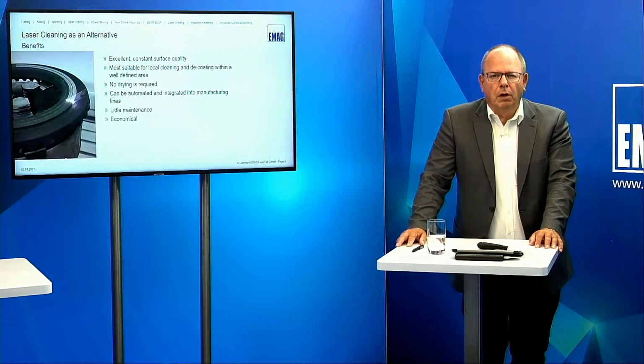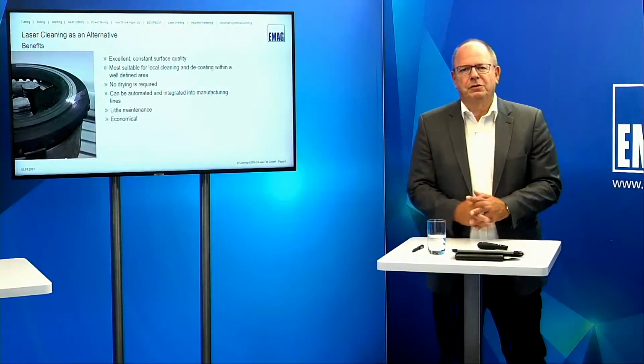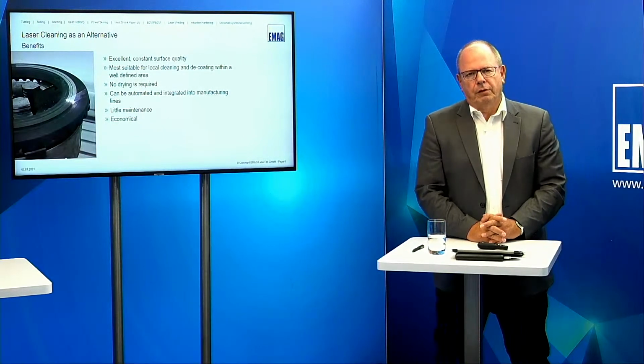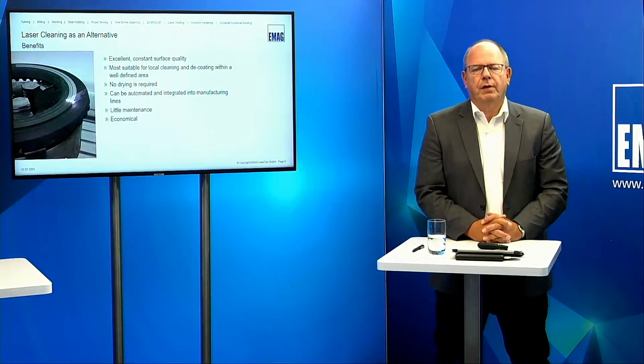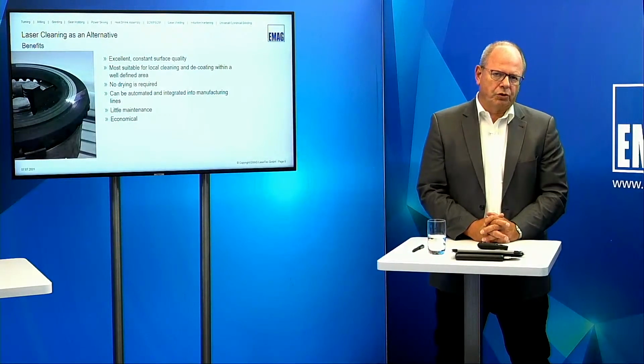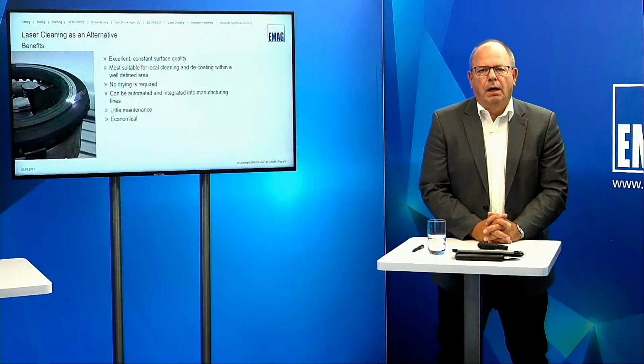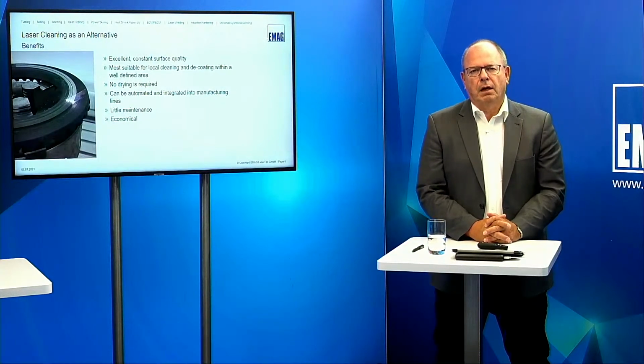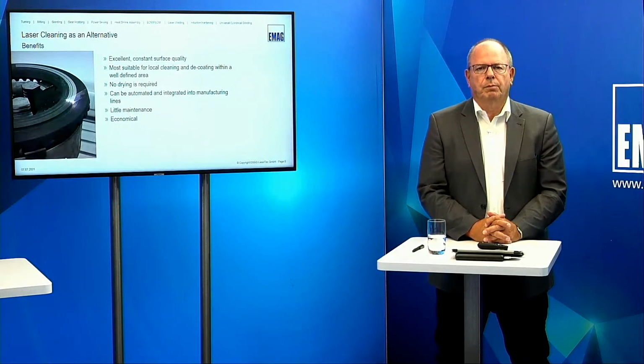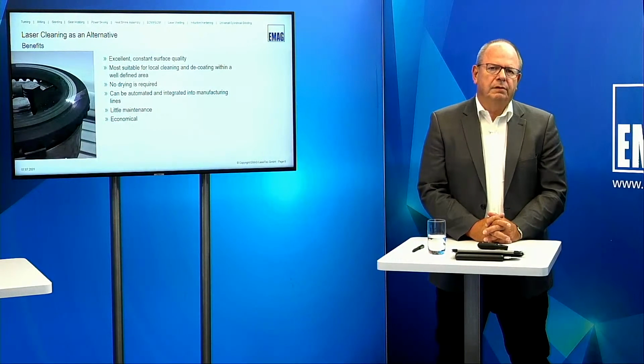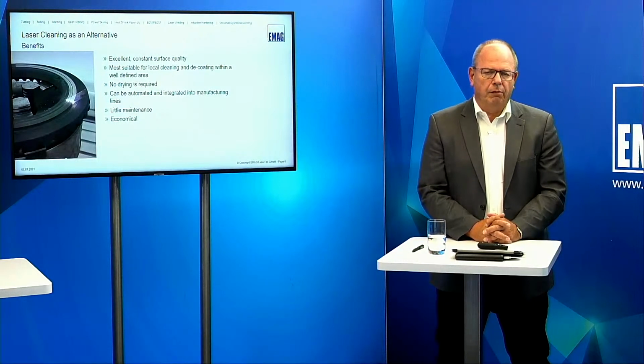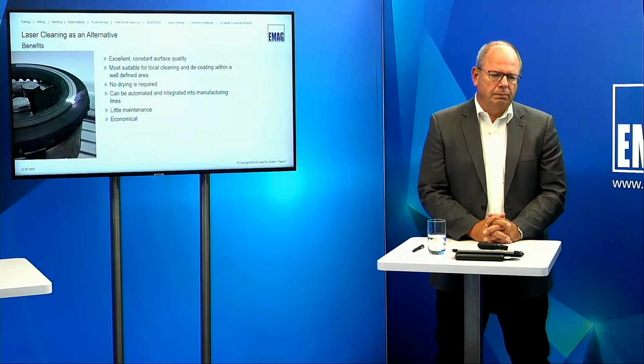Laser cleaning does not require part drying. Why do I mention this? In many cases, an alternative to laser cleaning, the older and more established process is conventional washing in a 3-zone washer. Wash, rinse, dry. And the lack of dryness is, in many cases, the root cause for problems in the following downstream process. If it's gluing, if it's coating, if it's welding. If you don't have really dry parts, then you run into trouble, and this happens in real life very often. And laser cleaning is a dry process, and therefore we do not have that issue.